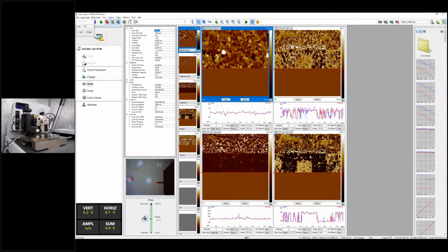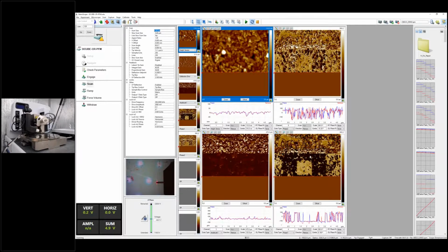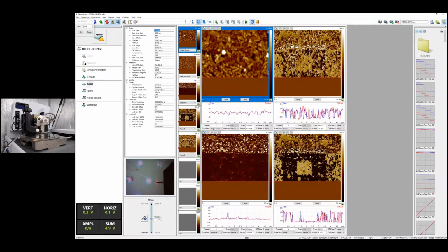This maybe looks quite simple, but it's also a quite straightforward way to test whether your sample is piezoelectric or not. So quite often, especially when people are talking about some 2D materials and also some conductive materials which they suspect have a piezoelectric response, the very strong evidence to prove that is to see whether you can do the poling of such material or not. If you cannot do the poling on it, even if you detect some piezo response signal from such materials, very likely it's just other electrostatic interactions involved or coupled into your piezo response signals. So this is about the poling.